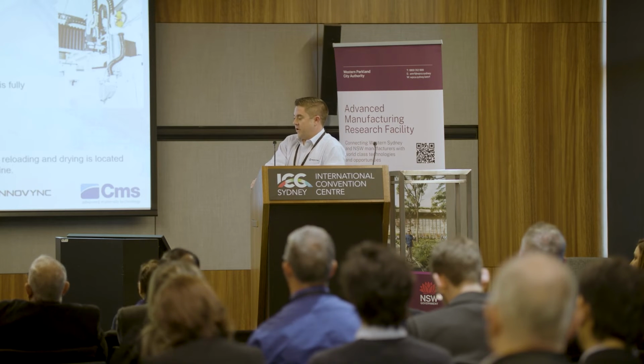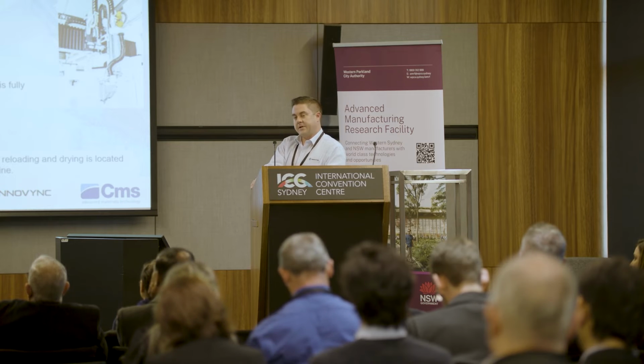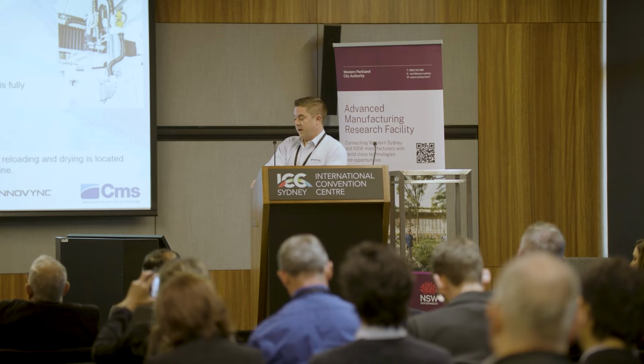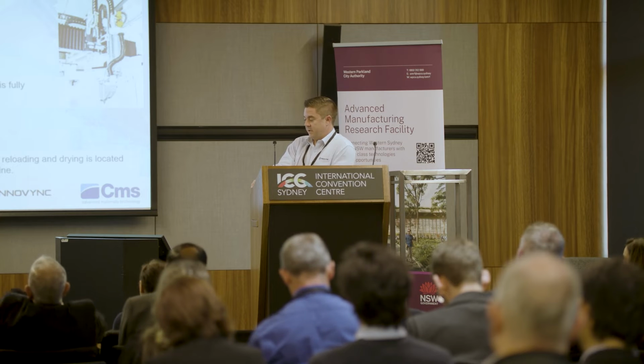The extruder uses a common HSK tool connection and it has a patent pending for the automatic connection, which allows the machine to interchange between extruder and milling tool without any human intervention. The extrusion is via a single screw extruder. The melting of the material is performed and controlled inside the extruder using friction. The melted polymer exiting the extruder is deposited in layers that plasticise and form a single part.